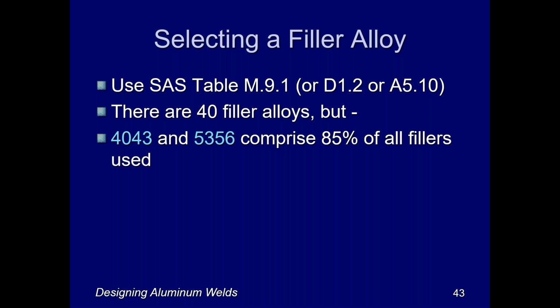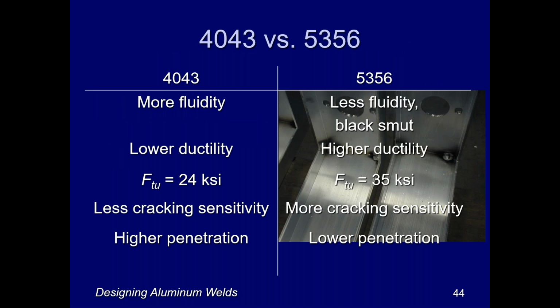Now, if you want to just follow the rules and avoid hot cracking, you can just select a filler alloy using tables that are given either in the specification for aluminum structures or in D1.2 or in A5.10, the AWS publications. And it can seem really complicated because there are 40 different filler alloys listed in A5.10, for example. But 9 times out of 10, well, or 85% of the time, I'll say, it comes down to 4043 or 5356. And just to compare those two for a moment, 4043 is a little more fluid, a little less viscous, and it doesn't suffer so much from the black smut that's produced by the high magnesium content of the 5356 filler. But 4043 is less ductile and has lower strength than 5356.